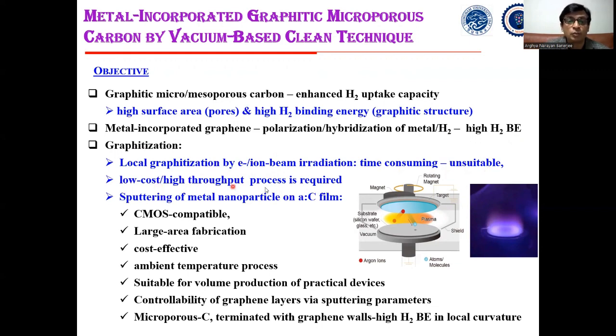We need some low cost, high throughput process for practical applications, and one of them is sputtering of metal nanoparticles on amorphous carbon film. So the importance is that the sputtering technique is CMOS compatible, large area fabrication is possible, it is cost effective, it is an ambient temperature process, therefore suitable for volume production for practical devices. Also, the number of graphene layers can be controlled by controlling the sputtering parameters. And this microporous carbon terminated with graphene walls can have very high binding energy at the local curvature.